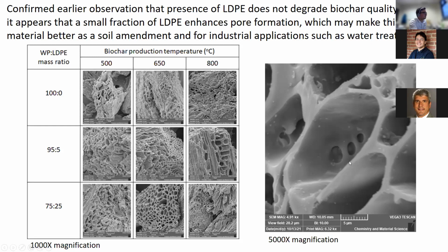And this implies that biochar will actually have a higher water carrying capacity and may also enhance the ability to support the microbial community in the soil. This is consistent with results that have been published in the literature showing that small amounts of plastic combined with biomass actually produce biochar of higher quality. So that would be our high level conclusion. Co-pyrolyzing small amounts of agricultural mulch film material with biomass produces biochar of high quality, and there's evidence that it may actually be higher quality for some applications.